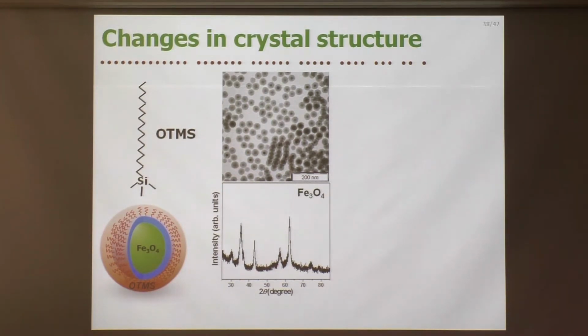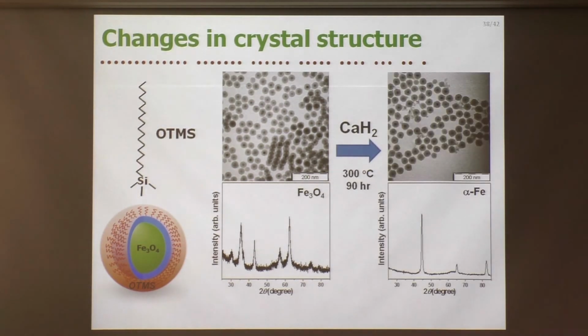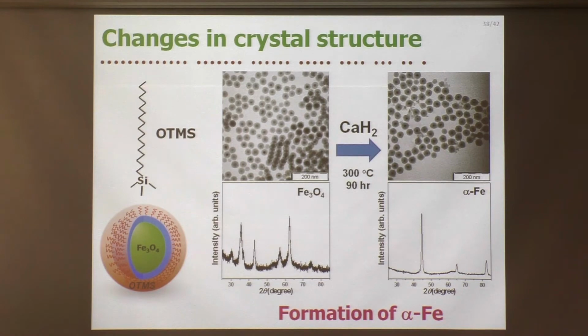Here shows the case of alkyl chain modified samples. Here is the TEM image and XRD pattern before reduction, and here is the TEM image and XRD pattern after reduction. Particle shapes are okay, and we can see the formation of alpha iron.